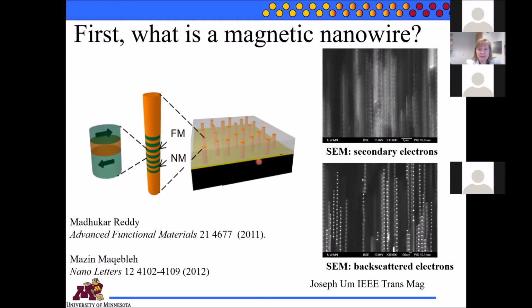So you coat the backside of it, and then you use the backside to electroplate magnetic nanowires inside the pores, and you can change the component, the concentration, the length, depending on what template you use. You have different diameters available. And we found different ways to image the uniformity of our wires.